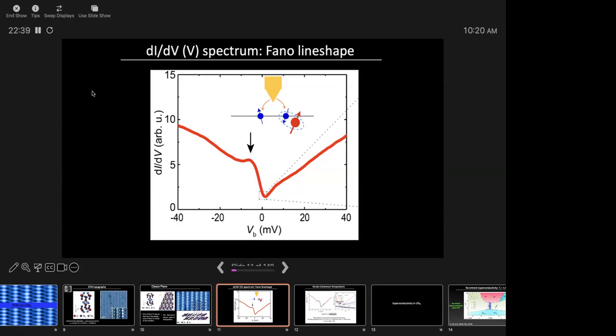When you see this line shape, what you should imagine in your mind is that there's a sharp resonance at this energy sitting right here. So there's a sharp peak in the density of states here, but the problem is we're not able to access that directly. The tunneling into that sharp state is highly suppressed because that sharp state has F character, and F orbitals don't stick out into real space. And because tunneling into that is suppressed, and there's this interference, you get this Fano line shape that we see in STM data of basically all heavy fermion compounds.